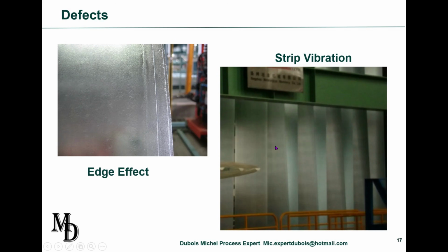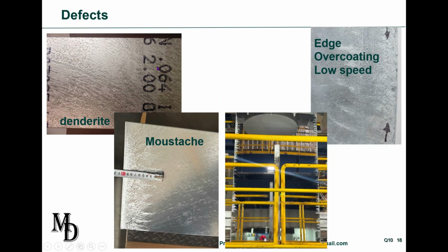You can see in the picture here there are dark and bright areas. This is because of strip vibration. But considering the pitch that we see here, most probably it's related to pot rolls. We have, in the case of spangled material and heavy coatings, this heavy coating being a 40 micron zinc coating, those dendrites. It means that the solidification is not straight. The spangles are very long.